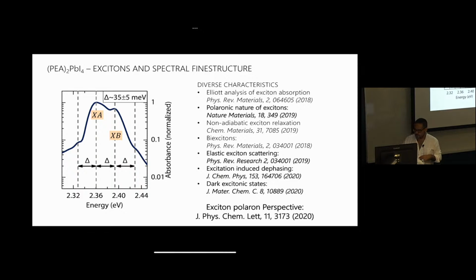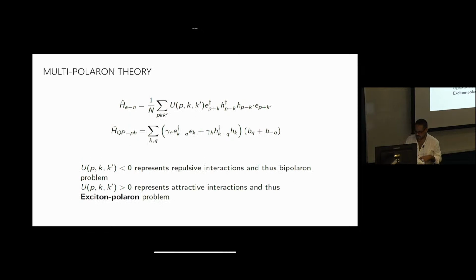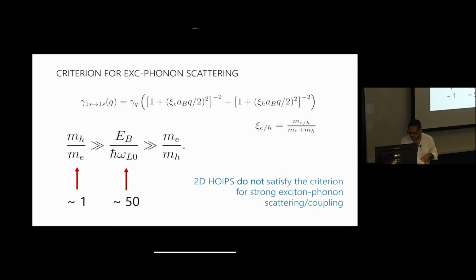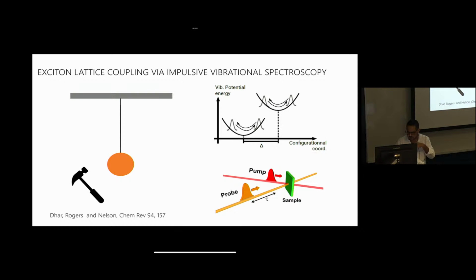So we go off and do that, but we don't do that in the frequency domain. We do that in the time domain. Let me not go through all of this too carefully. Let me skip the theoretical argument here, and let me just go to the experiment. We do this in the time domain. The experiment that I'm going to show you right now is you excite with a short pulse, a femtosecond pulse, and then you do a pump probe experiment.